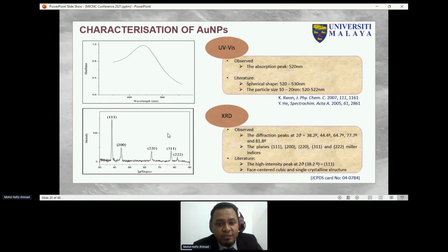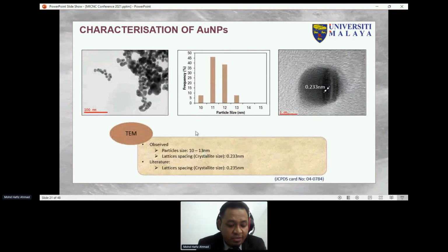And for the characterization of gold nanoparticles, the UV-Vis spectrum shows the absorption peak of gold nanoparticles at 520 nanometers. This peak gives the information that the gold nanoparticles synthesized are spherical in shape and 10 to 20 nanometers in size, after comparing with literature. And here, as we can see, this is the typical XRD pattern, and signature peaks of gold nanoparticles were observed in this spectrum. For the TEM image, the image of synthesized gold nanoparticles shows the particle size in the range of 10 to 13 nanometers.